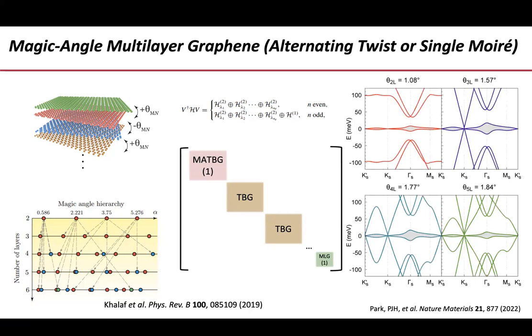Two layers, just a flat band. Three layers, flat band plus the cone. Four layers, flat band plus large twisted bilayer graphene. Okay, that's not a direct cone, that's large angle twisted bilayer graphene. Five layers, you get flat band, large twisted bilayer graphene plus direct cone. Okay, and so forth, and you keep going.